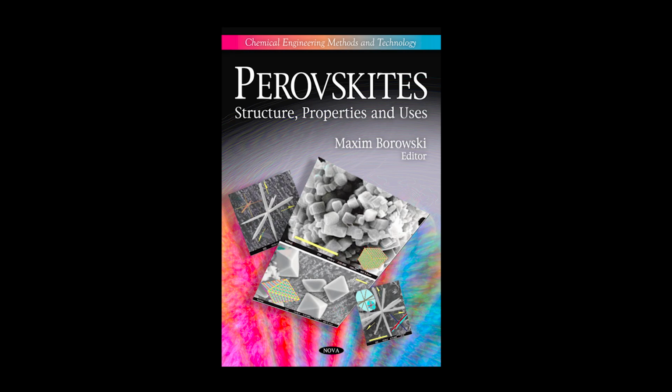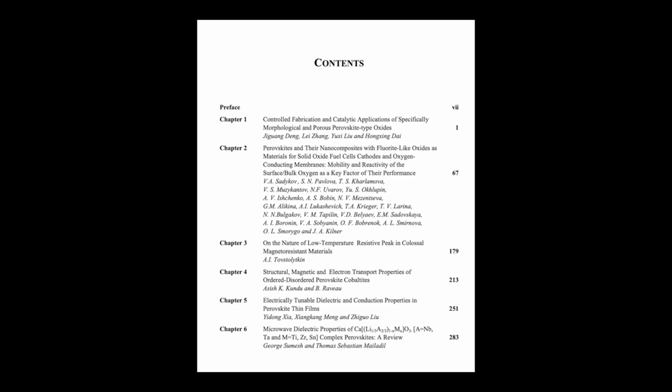Right. For a stable perovskite structure to actually form, T must strictly fall between 0.75 and 1.00. If T equals 1, bingo. You get that perfectly stable, ideal cubic structure, zero internal strain. Everything fits just right. But as T deviates downwards, say T is less than 1, the A cation is effectively too small for the space it's supposed to occupy in that cubic structure. The result is that the entire lattice compensates by initiating that structural rotation or, more commonly, tilting of the BX₆ octahedra.